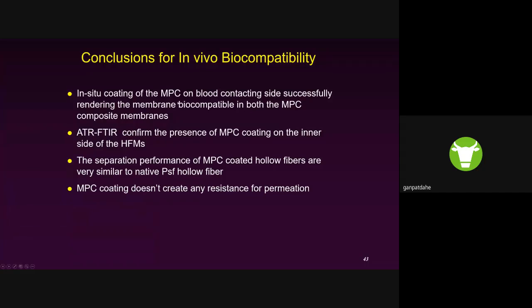And the presence of those polymers is not impacting the porosity as such, and it is showing very similar porosity to that of the pure polysulfone membrane. These studies conclude that this is also a good way of increasing the biocompatibility of the membrane, where mostly the blood contact happens on the lumen side. So it is very critical to increase the biocompatibility of the lumen side. So this is the second part of the study that we did.